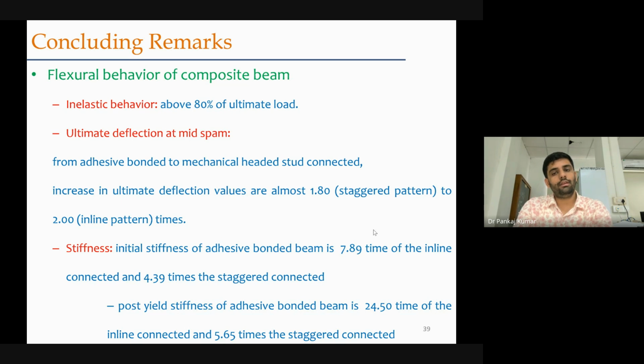In case of mechanically connected, to be precise, it was 1.8 times for the staggered pattern and 2 times for the inline pattern. And then when we compared the stiffness, we found that adhesive bonded specimens were more stiff. So this was more initial stiffness, roughly about 7.89, or we can say almost 8 times of the inline connector, and almost 4.4 times the staggered connector.